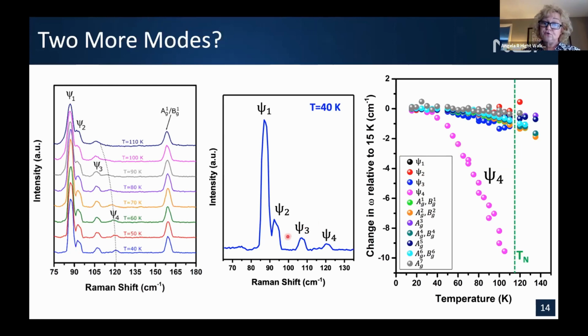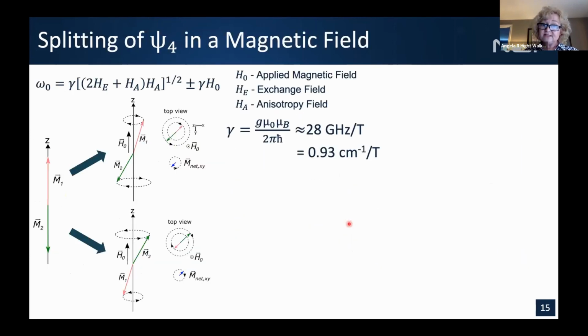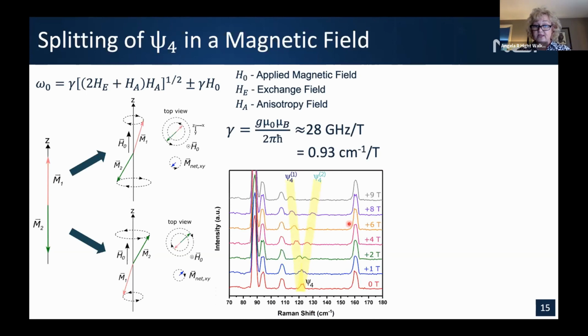So again, these two features cannot really be explained by the zone folding that we spoke of just a bit earlier. And with that Psi4 behavior being so rapidly changing with temperature, we thought perhaps it could be a magnon, a spin wave. And there is a pretty easy way to see if it is a magnon, and that is to put it in a magnetic field, where in this case, the magnetic field is perpendicular to the AB plane of the iron PS3. If it is a magnon, one would expect that the feature would split in magnetic field, and that splitting would happen at about a wave number per Tesla.